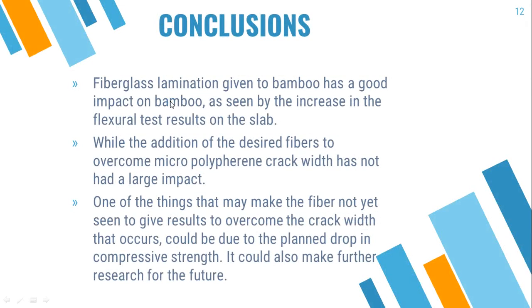To conclude: first, fiberglass lamination given to bamboo has a good impact on bamboo, as seen by the increase in the flexural test result on the slab. Second, the addition of micropolypropylene fibers to overcome crack width has not had a large impact. Third, one of the things that may keep the fiber from showing results in overcoming crack widths could be the drop in compressive strength. It could also inspire further research in the future.